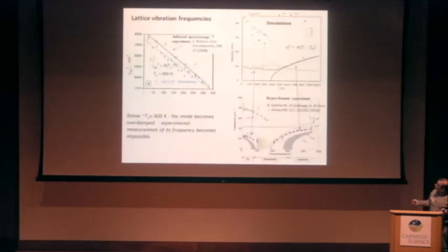I cannot say that there is only one mode. Maybe yes, but the second mode, the higher frequency mode, exists in neutron scattering, and coupling plays a role. Thus, what about this mode, the third mode, at intermediate frequencies? According to one of your explanations, this is the mode related to chemical ordering. We cannot observe this mode because our model is completely disordered. Okay. What is observed above Burns temperature, we observe in this case only one mode. The second mode